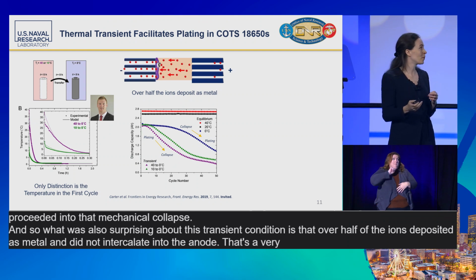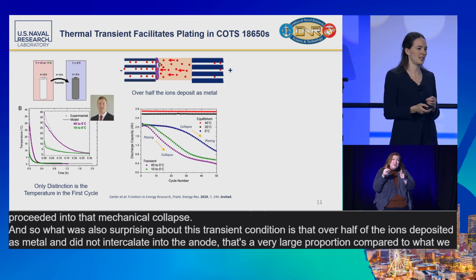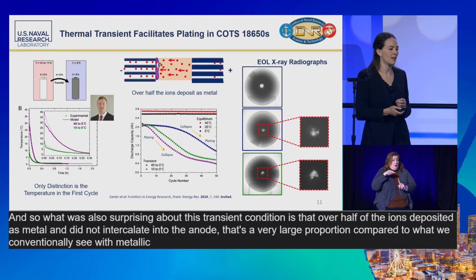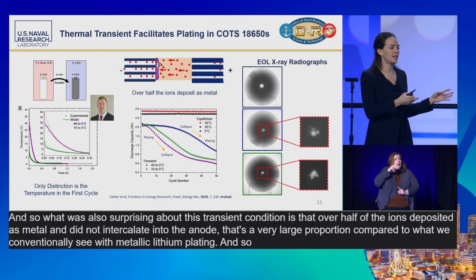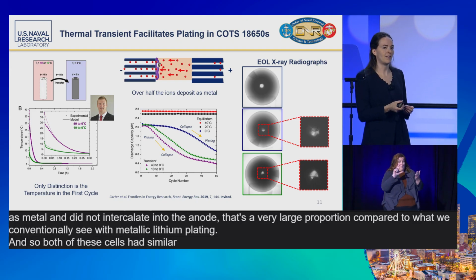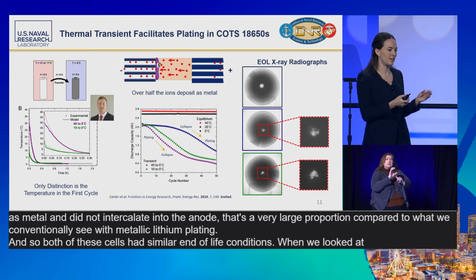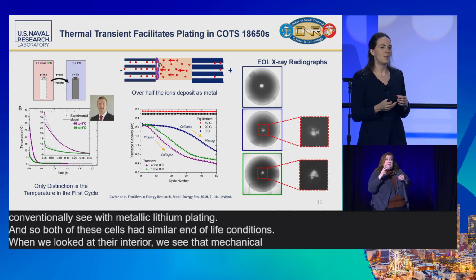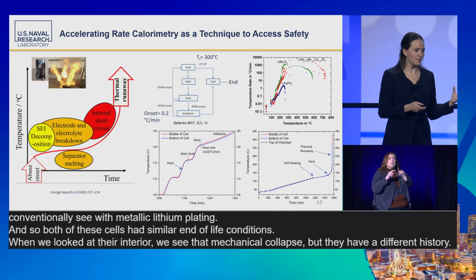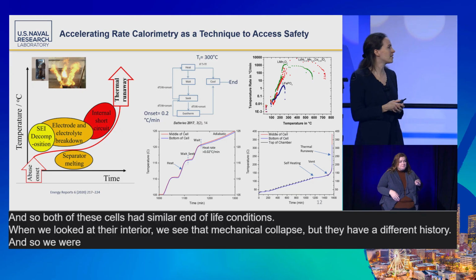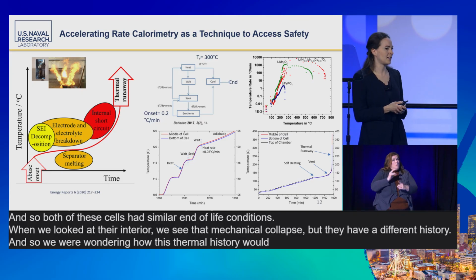That's a very large proportion compared to what we conventionally see with metallic lithium plating. And so both of these cells had similar end-of-life conditions. When we looked at their interior, we see that mechanical collapse, but they have a different history. And so we were wondering how this thermal history would impact their safety.